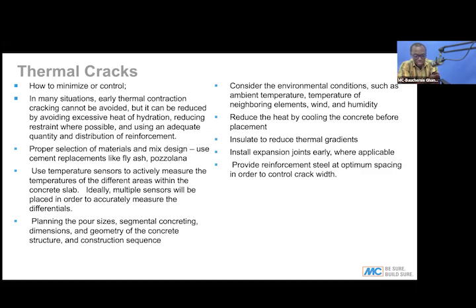Secondly, in some cases, you may even have to use cold water for the concrete. And that can also regulate the inner core temperature of the concrete. In some cases, in Dubai, for instance, most of the constructions, they install pipes in the concrete where they run cold water through the pipes. So as they cast the concrete, there are pipes installed in the concrete. Then as the concrete is hardening, they run cold water through the pipes. And that helps control the temperature of the concrete.